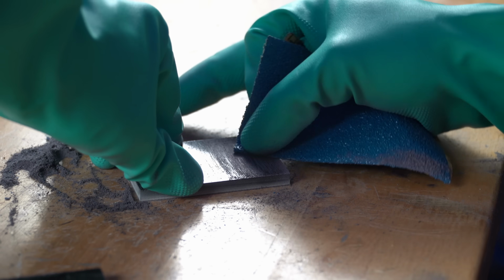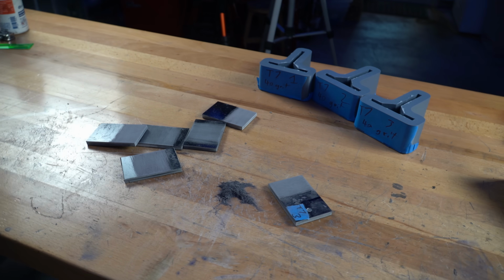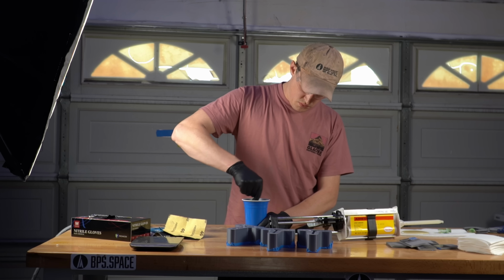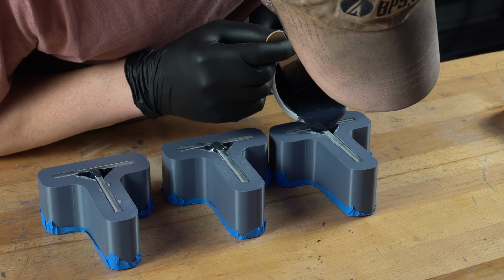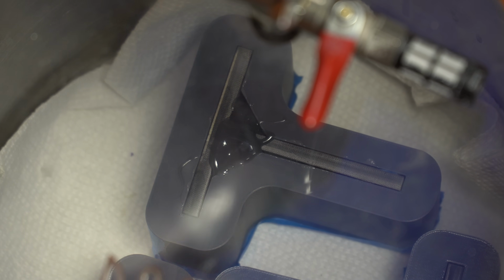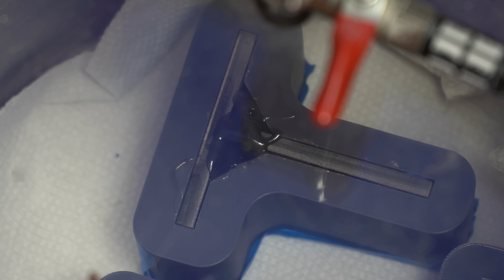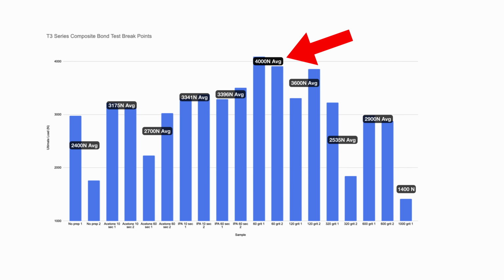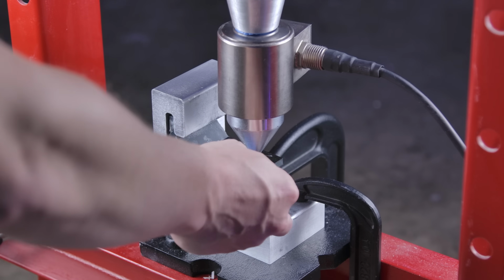Just as always, after sanding, I wiped the surface clean using lint-free wipes and high-grade isopropyl alcohol. Then I mixed up another batch of epoxy with a little black dye, degassed in the mix cup, poured it into the mold, then re-degassed in the mold to get as much strength as I could. I was hopeful and trying with every technique I knew to get back to that 4,000 Newton number, and when the epoxy had cured for 48 hours... Oh, wait.